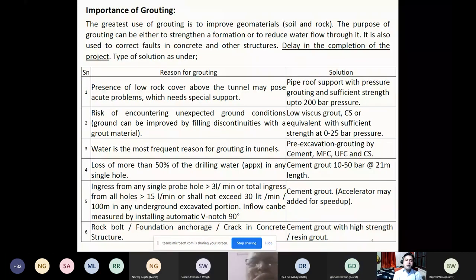Thank you. With the presence of low rock cover, the tunnel may pose acute problems which need special support. Pipe roofing support with pressure grouting can be done up to 200 bar pressure, and if the strata is not permitting a sufficient amount of pressure, then the pressure of grout can be reduced, like 0 to 25 bar. Then if the ground condition is okay but cover is insufficient, then we can increase the pressure. Then next is the risk of encountering unexpected ground conditions, and low viscous grout and colloidal silica will be better in this case, and 0 to 25 bar pressure will be okay.